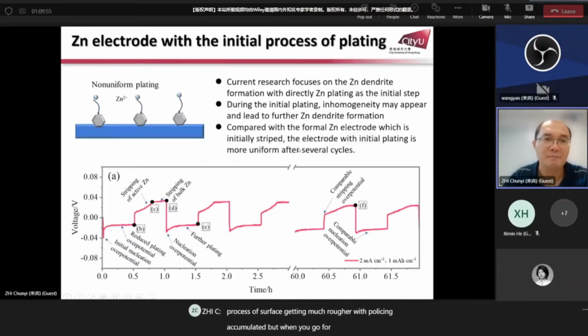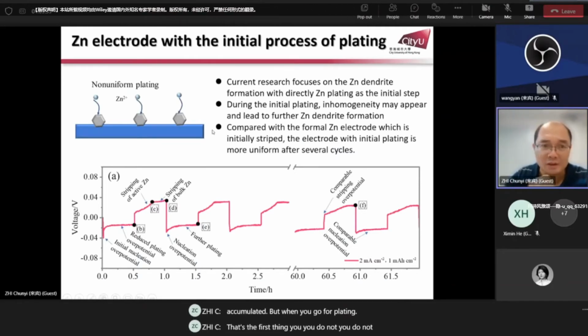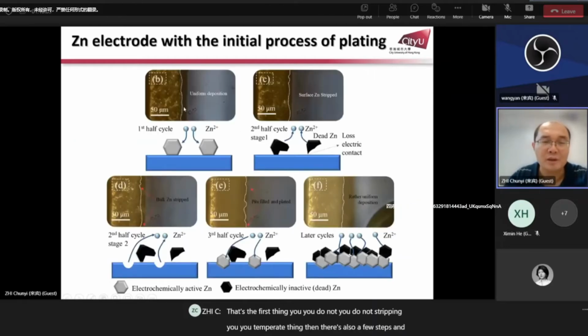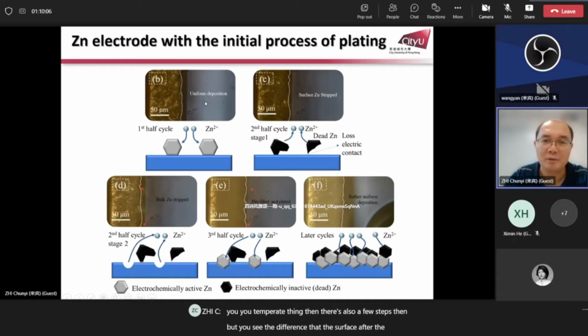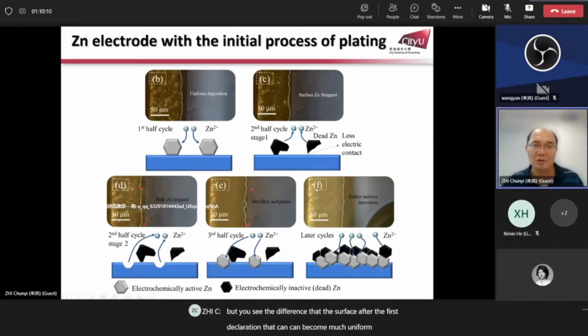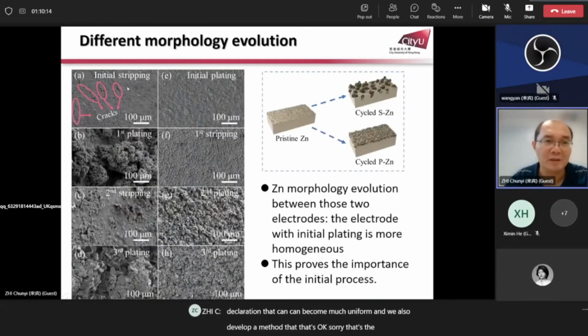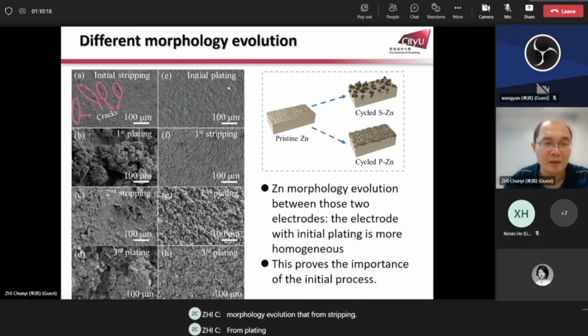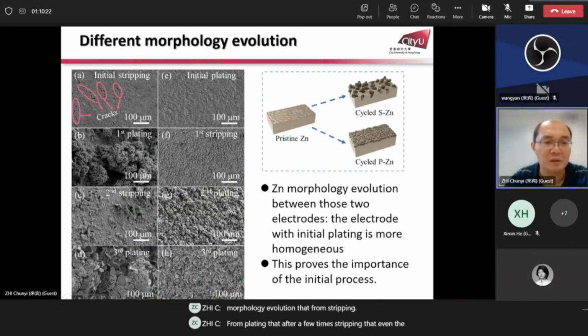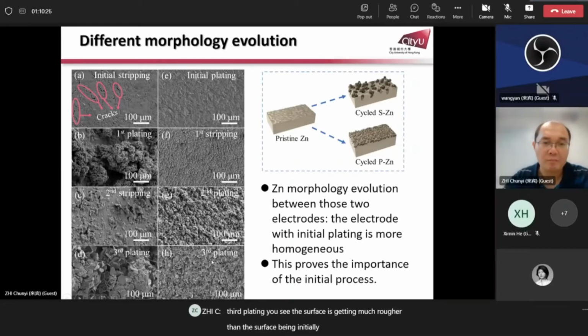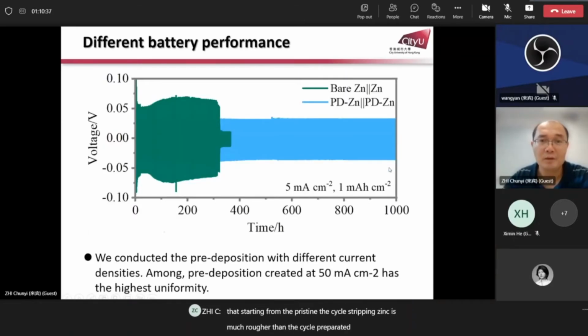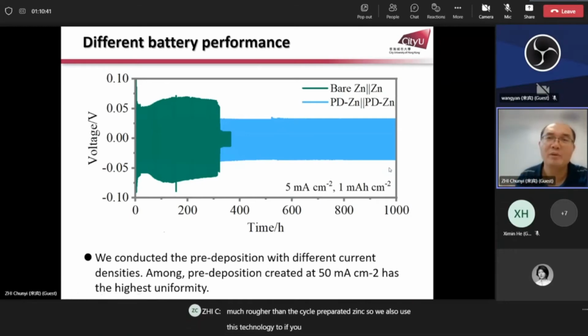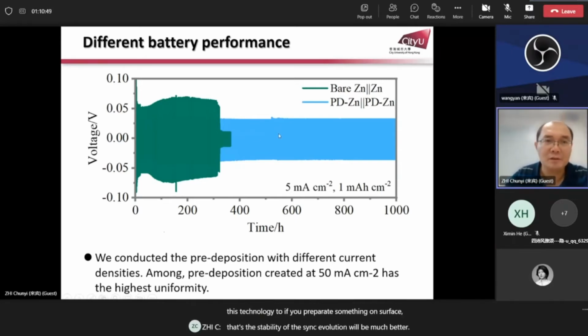But when you go for plating, first you do not strip, you deposit the zinc. Then there are also a few steps, but you see the difference: the surface after the first deposition can become much more uniform. And we also developed a method for the morphology evolution, from stripping to plating. After a few times of stripping, even at the third plating, you see the surface is much rougher than the surface that was initially plated. So this is the evolution starting from the pristine: the cycled stripping zinc is much rougher than the cycled pre-deposited zinc. So we also use this technology: if you pre-deposit some zinc on the surface, the stability of the zinc evolution will be much better. So this is one of the observations.